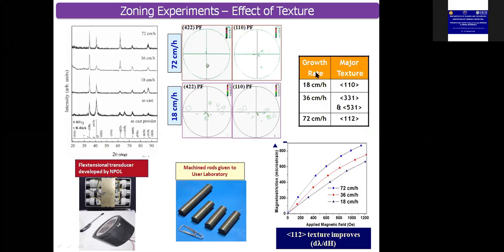To our surprise, when we change the growth rate, the textures are different. At a higher pulling rate, we got a texture very close to the 112 direction. If you see the angular orientation between the 111 direction, which is the easy direction of magnetization, and the 112 direction, that misorientation is less. Since the misorientation is less, we have a very near orientation along the 111 direction. We have got a high magnetostriction when we pull at higher pulling speed. So this essentially signifies that not only the microstructure is important, it is also important to have a good texture to have high magnetostriction.